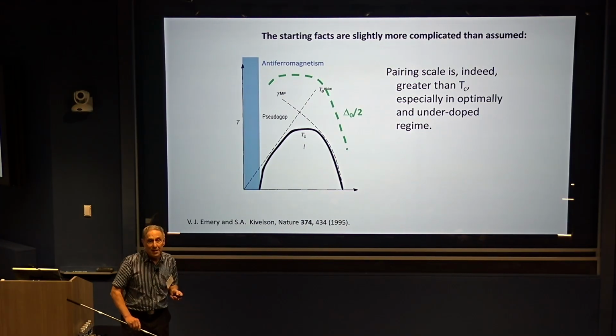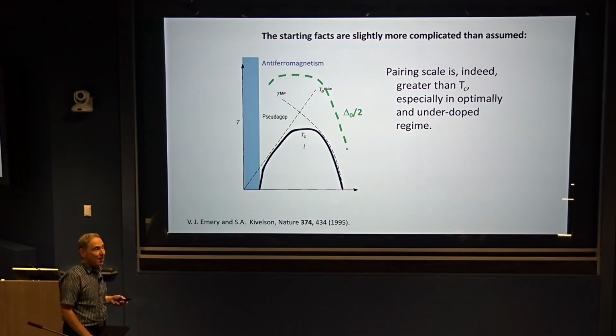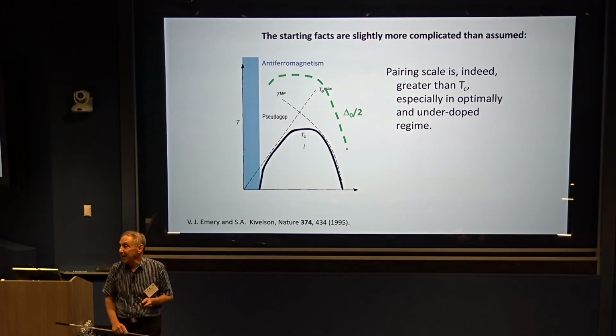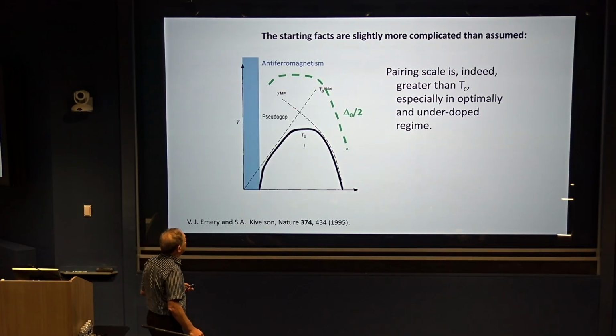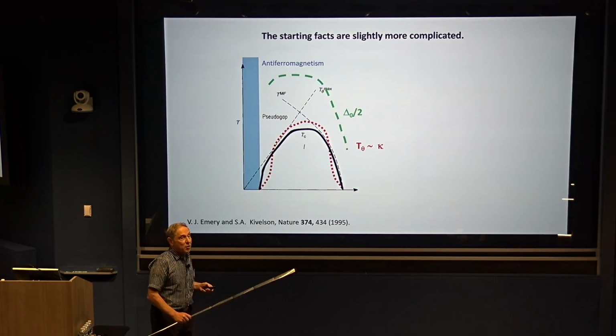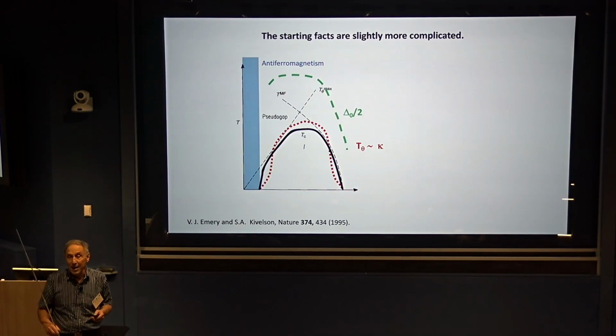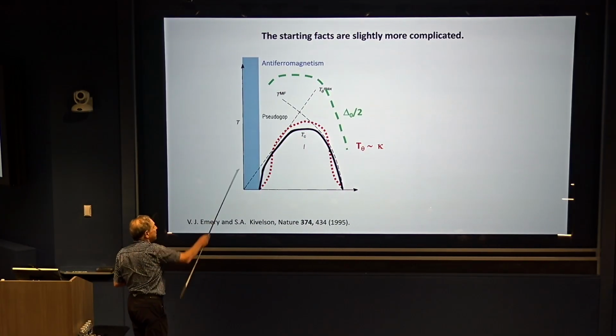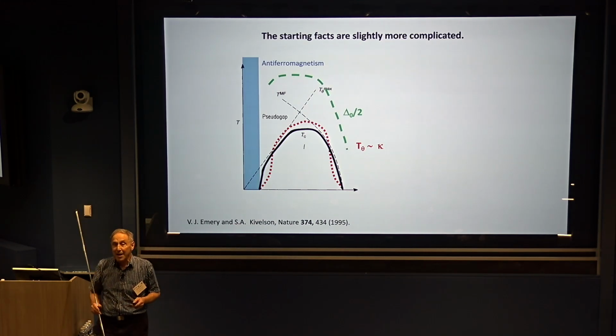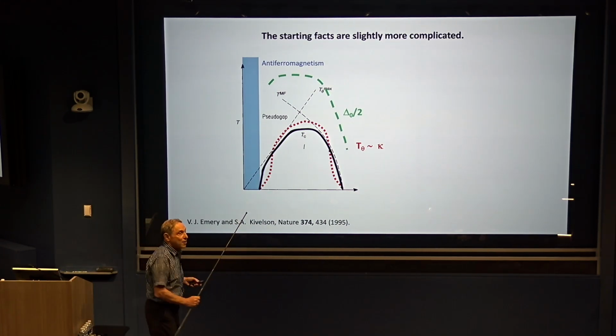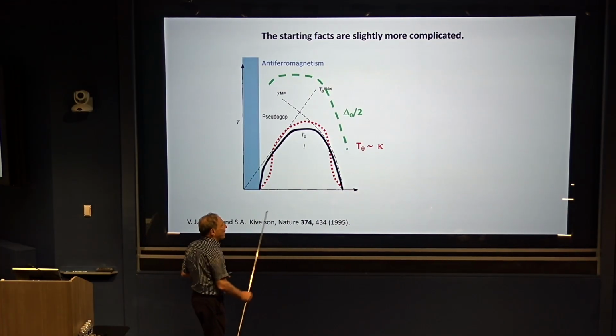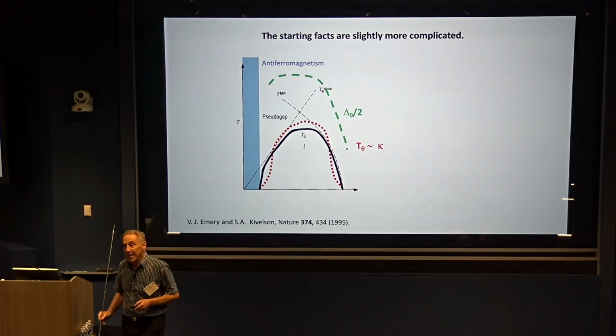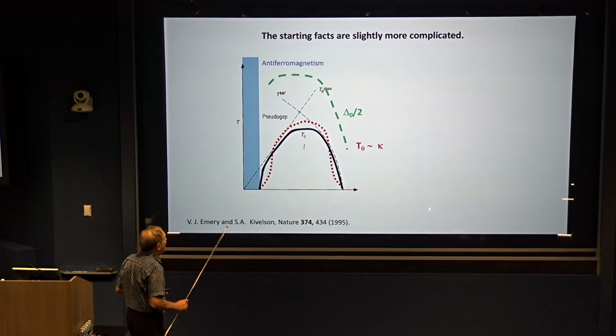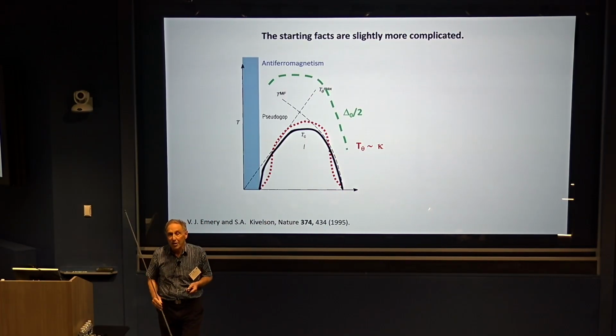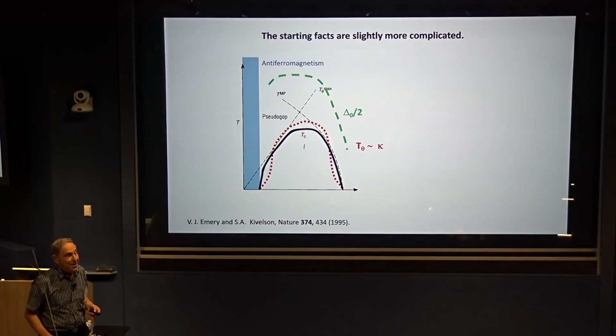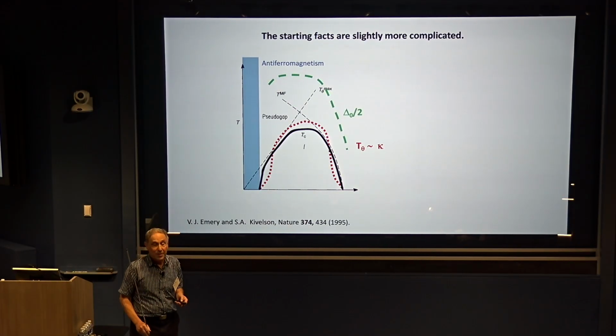So the pairing scale is not what determines TC in the underdoped regime. The pairing scale is such that you might have expected a much higher TC were it not for phase fluctuations. Now, the superfluid density turns out not to do what we expected. It does track with TC on the underdoped side, so that's fine. That's consistent with TC being determined by phase ordering. But many experiments now show that it also drops with TC on the overdoped side. So TC again has a significant contribution from phase fluctuations, and the phase stiffness becomes really small on the overdoped side.